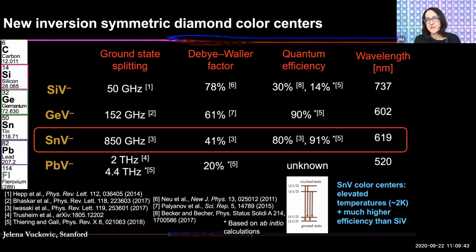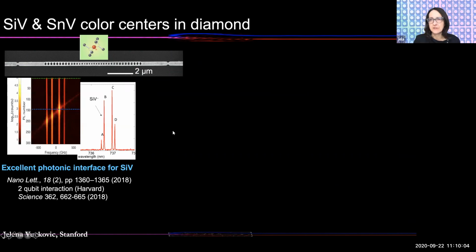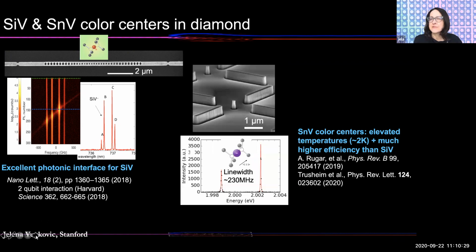As opposed to silicon vacancies, you can do experiments in closed cycle cryostats at several Kelvin of temperature, and also tin vacancies have significantly higher internal quantum efficiencies than silicon vacancies. So what is the state of the art for these color centers? For silicon vacancies, I'll very briefly summarize that people have demonstrated excellent photonic interfaces for silicon vacancy inside of a diamond resonator. People have also demonstrated 2-qubit interaction for 2 silicon vacancies inside of the same cavity that are tuned with magnetic field. That was the work at Harvard. So people are pretty much at the level of scaling corresponding to 2 qubits. And also for tin vacancies, research started to ramp up about a year ago.